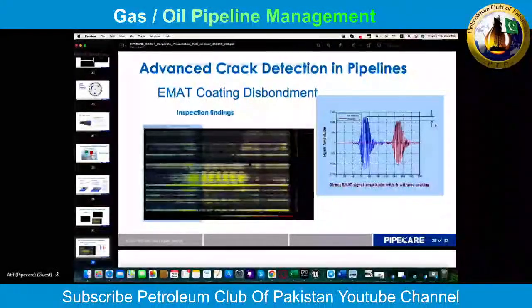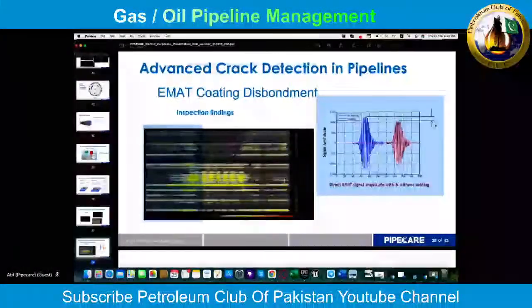And the coating disbondment is determined by checking the amplitude of the reflected signals. Because when the coating is disbonded, the reflected signal is stronger, approximately 2 dB stronger than a signal which is reflected from a pipe wall which has a coating. Now, of course, there is a certain area required to be certain that there is a coating disbondment, and this area is approximately 6 by 6 centimeters. Only if there is a total disbondment of that area can we be sure that there is really a coating disbondment. Okay, next.